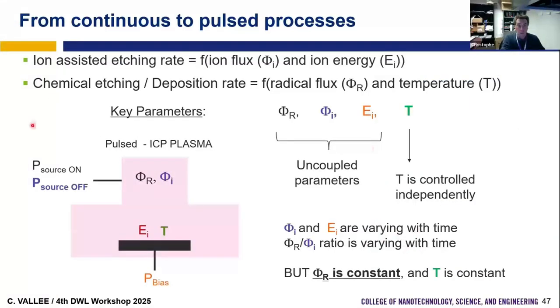Okay, so this is what we have by pulsing the plasma. Now we use HDP source to decouple, and now we pulse the HDP source. So if we pulse the HDP source, we decouple, but we also vary with time the ion flux and energy and vary with time the radical to ion flux. But the radical flux is still constant because, as I said, the radicals survive longer than the off time. So we do not really modulate the radical flux by pulsing, and temperature is still constant.